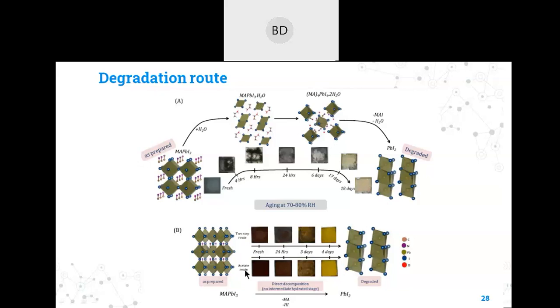But in the case of the two-step route and the acetate route, it goes directly to the lead iodide film. If you see here, after 24 hours, no significant degradation can be seen in the perovskite films. But after a prolonged exposure of around 3 or 4 days, you can see a clear white color of lead iodide. Here the color is not clear enough to show the PbI2, because some water is still there in the structure, and some PbI2 has already dissolved with water. So you cannot see a clear PbI2 color here, but here it is clearly visible.